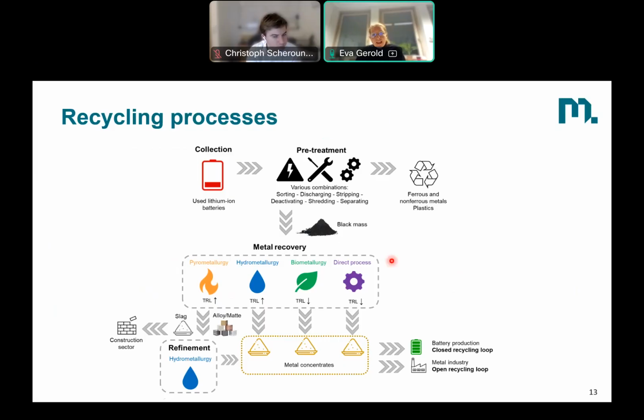Coming back to the recycling, after we now know what our black mass, our input material, is, we need to go on to metal recovery, so to metallurgy. The first option is pyrometallurgy, with a quite high technological readiness level, where you smelt your black mass and produce an alloy composed of cobalt, nickel, and copper mainly. Manganese and lithium are mainly slagged, and actually that's the biggest problem in this process, because you have quite low residual lithium contents in your slag, approximately 1 to 2%, and you could leach the slag and extract lithium, but this is currently not economically feasible.